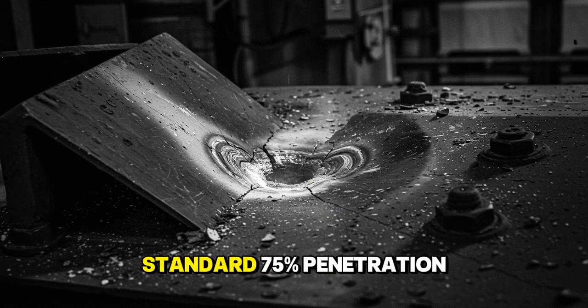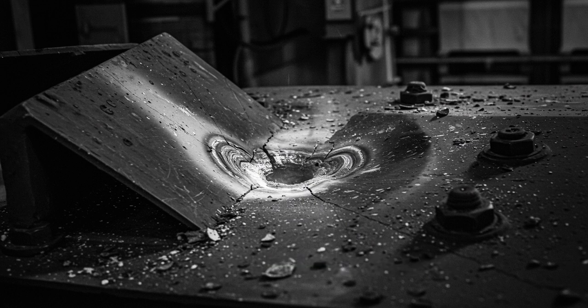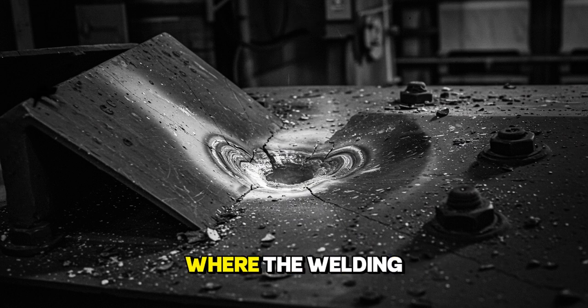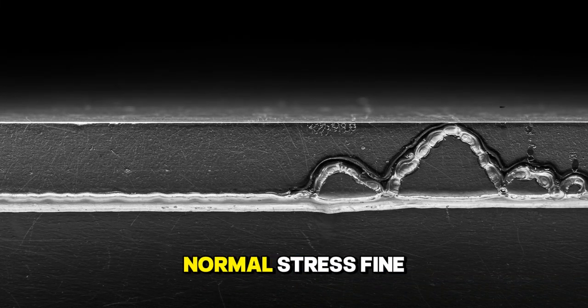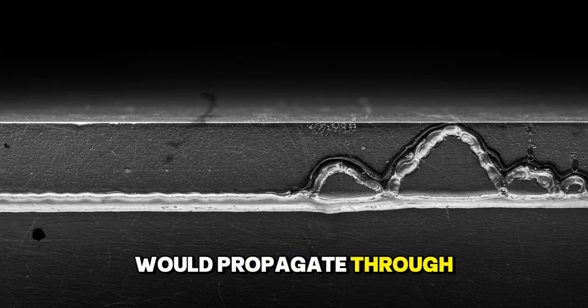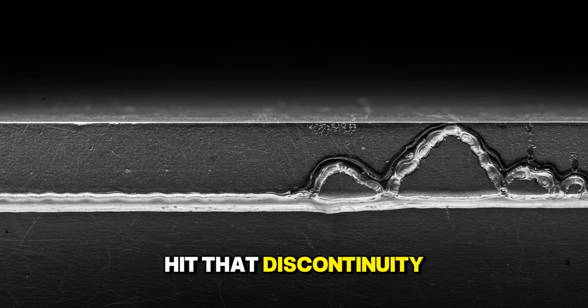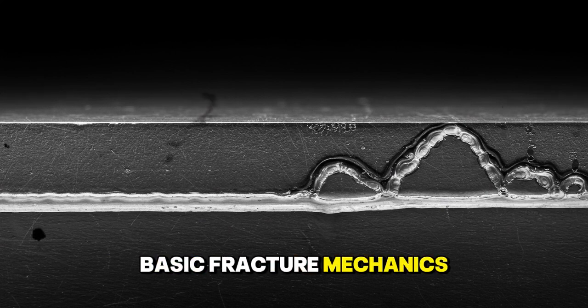In the Army's standard 75% penetration weld, you had a large HAZ on the outer surface where the welding was done, but the inner 25% of the plate, the root, never got hot enough to truly fuse. It was just sitting there, held in place by the mechanical constraint of the weld above it. Under normal stress, fine. Under high-velocity impact, that unfused root became a crack initiation site. The shock wave from an 88mm round would propagate through the armor plate, hit that discontinuity, and the joint would unzip like a zipper. Basic fracture mechanics.